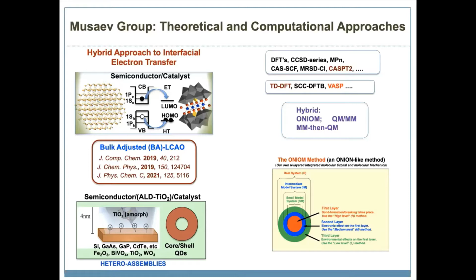Lately, we developed a bulk-adjusted linear combination of atomic orbitals approach. We also use this approach to study core-shell quantum dots. In other words, the core is, for example, gallium selenide, and the shell could be gallium sulfide, etc.